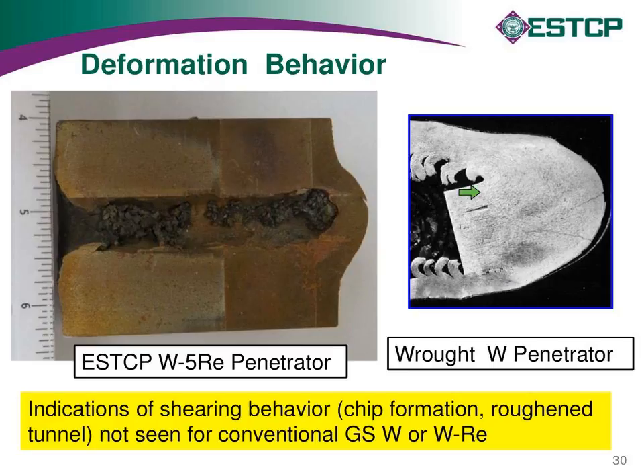The entire penetrator is still one piece essentially after the event. It's just been turned from a solid rod into a hollow tube. So we didn't have that happening here. We were definitely seeing some shear localization and discard behavior. I think that's why we're in the same neighborhood as the tungsten heavy alloys, which also display a little bit of this behavior with the tungsten nickel iron matrix. So we were getting a little bit of that behavior with essentially no matrix phase. It's just tungsten rhenium material. But again, we're still way far short of DU performance at this point.